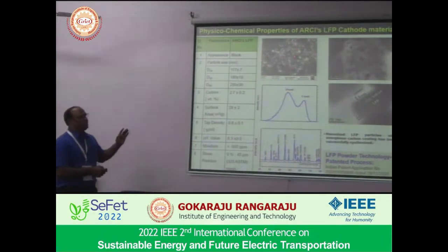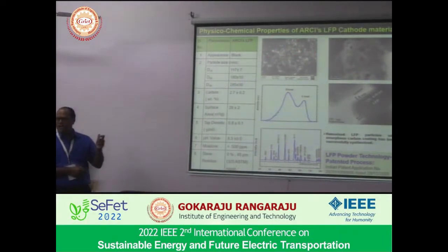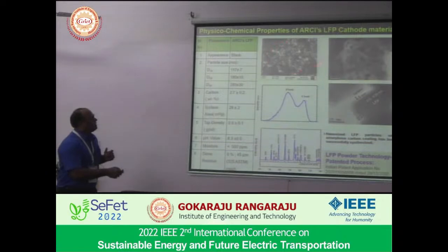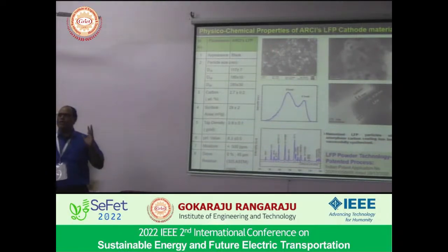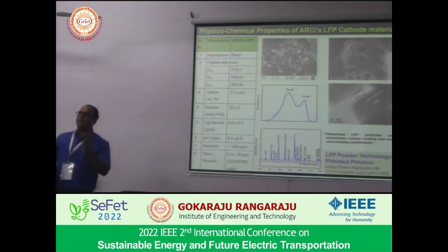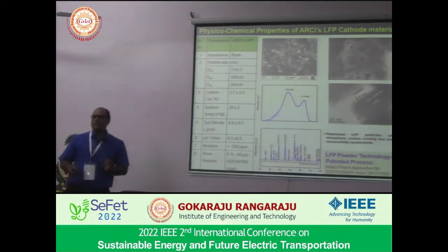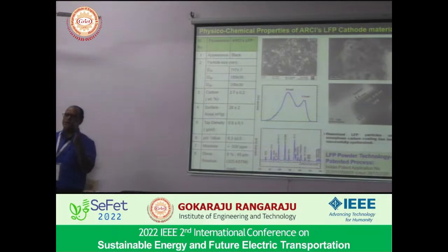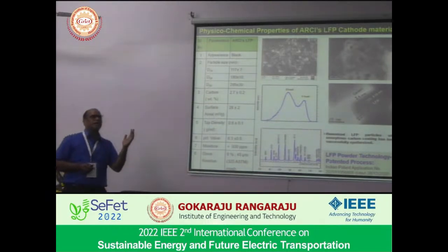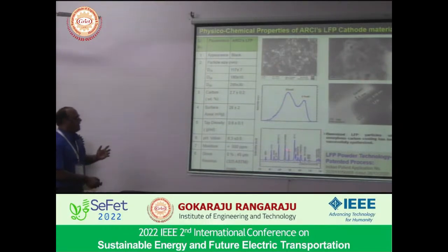As I have mentioned, the particle size is less than 100 nanometer. If you can see, all these particles are embedded into the carbon network. You need nano-size particles as well as uniform carbon coating, so that you can increase the lithium ion diffusion kinetics as well as electron transport. That's what we have done, and we got a pure phase of LiFePO4. So nano-size LFP particles with amorphous carbon coating have been successfully synthesized.